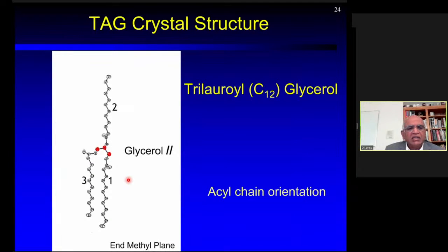Until the 1990s, when this work was done, there were only 2 crystal structures that were known. That was C10 and C12 triacylglycerols. The reason for that is that crystallizing these triacylglycerols into a good single crystal is difficult. That is why only 2 crystal structures are known. This triacylglycerol crystal structure is shown here with the acyl chain orientation. Let me take you through the molecular orientation of the triacylglycerol.